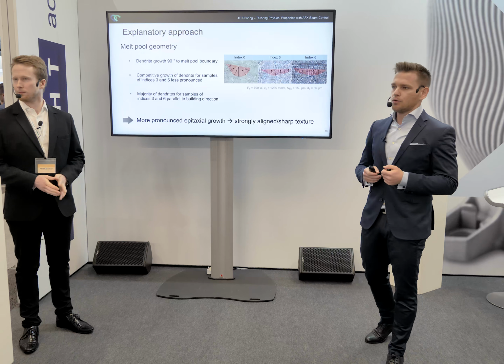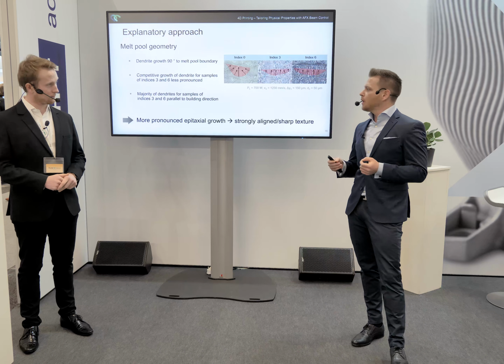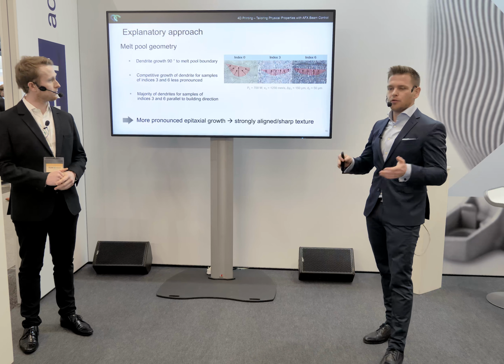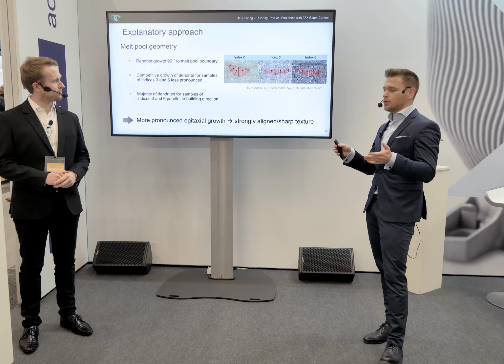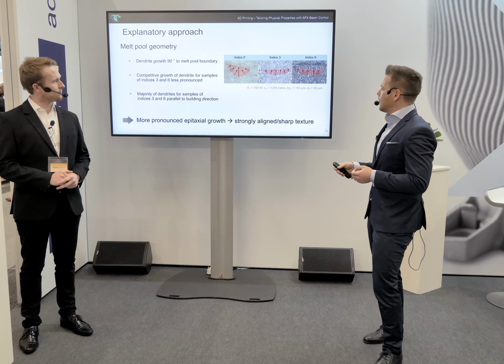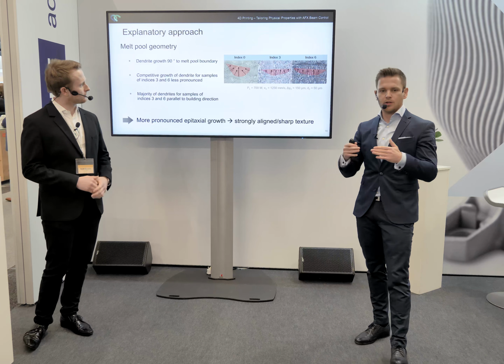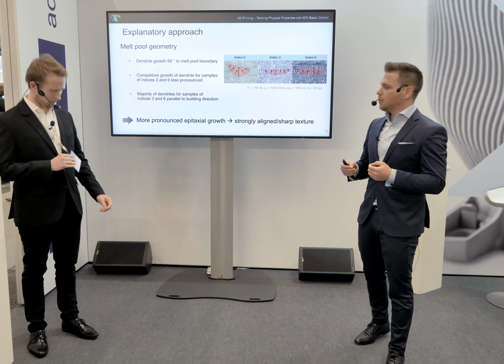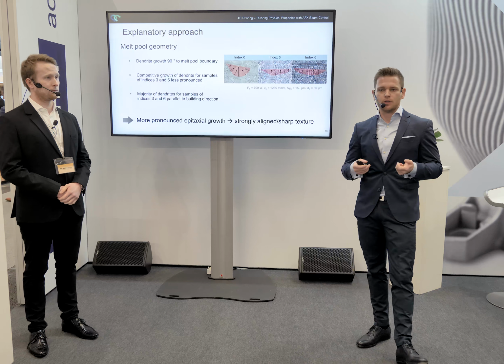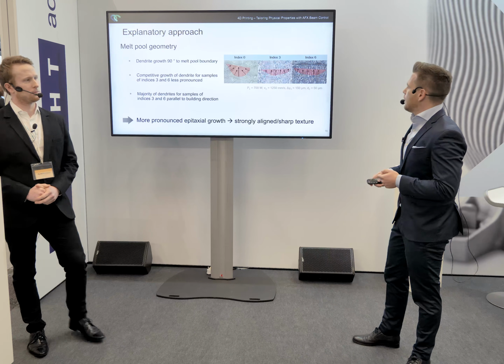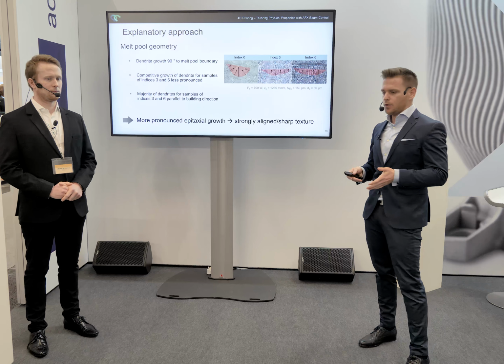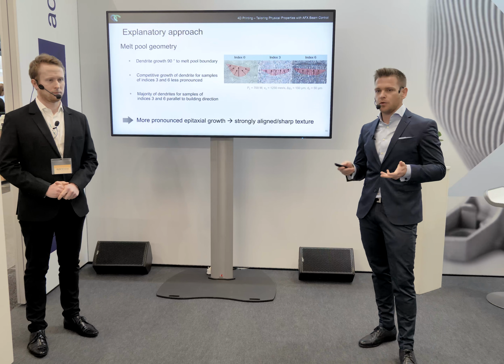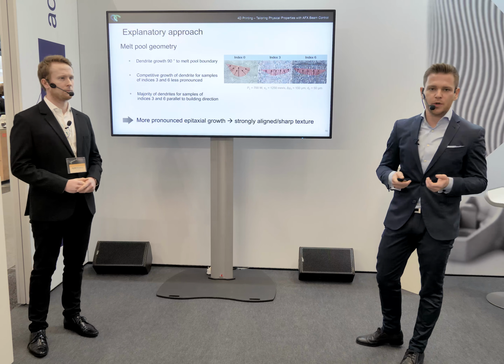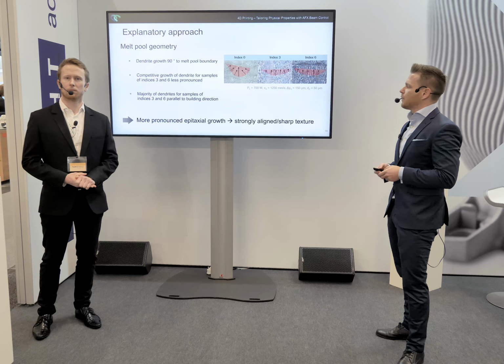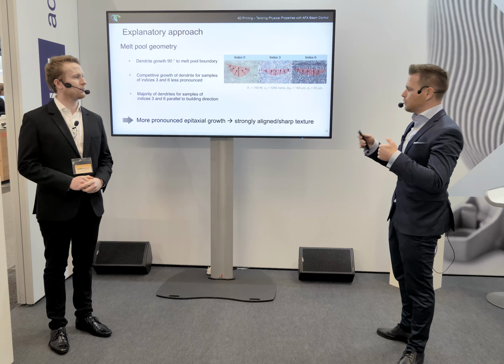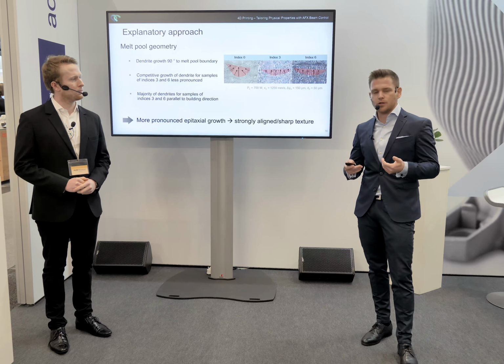And generally, the dendrite growth occurs perpendicular to the melt-pool boundary. In the case of a flatter melt-pool, we have more dendrites aligned parallel to each other and to the build and load direction, while on the left side we have dendrites growing to the center of the melt-pool, meaning a higher competitive growth of dendrites and thus leading to different grain orientations. While on the right side we have dendrites growing over many layers, and thus grains over many layers, giving rise to this sharp texture and the differences in the texture. So we can explain the different textures by the melt-pool shapes, and the different textures are the reason for the different mechanical properties.